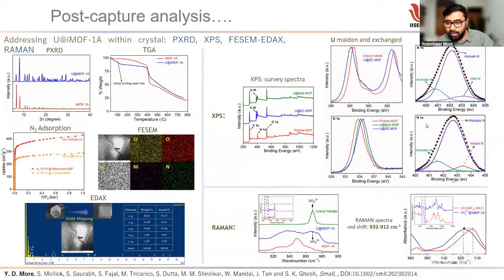Similarly, we have seen changes in the nitrogen and the oxygen of the MOF itself. Nitrogen is showing a significant shift. Hence, we got to know the nitrogen in the MOF is interacting with the uranium, because both show a significant XPS shift. Going further, the Raman spectra are also very impactful here. You can see uranyl nitrate has two humps for the uranyl cation in the Raman, and the uranyl nitrate above here has a single hump, and the MOF 1A at the bottom is the red line. But when we go to the composite, meaning the ion exchange phase where the uranium has been captured, you can see a composite of both the uranyl phase as well as the MOF phase. So peaks for both. That is indicative of the successful exchange of uranium within the pore. And then after this Raman, we further looked at how much the shift is.